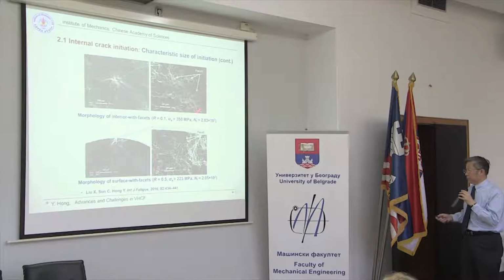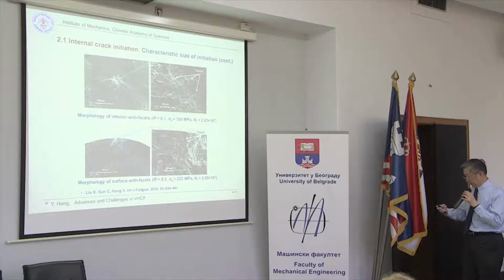Again, these are the examples from titanium alloys, initiation spot. And this picture shows the small pieces of fracture facets from alpha phase. This is another one, with stress ratio of -1, and stress ratio of 0.1 and 0.5.